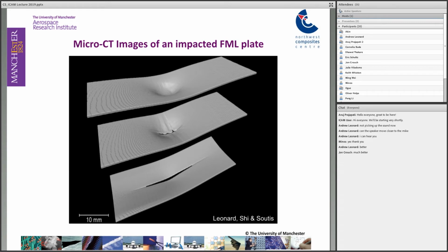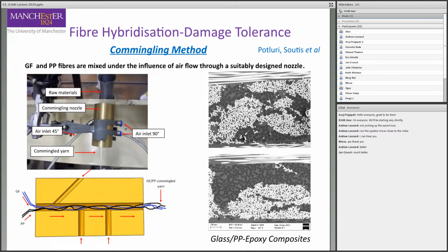Another way of achieving toughness and preventing early damage in the form of matrix cracking and delamination is if we can mix different fibers together. In this example, for instance, we have glass fibers that provide the strength and the stiffness in our construction, mixed with polypropylene fibers that provide this additional toughness in our composite system. They can sustain higher strains, and they make it harder for the composite to get damaged.